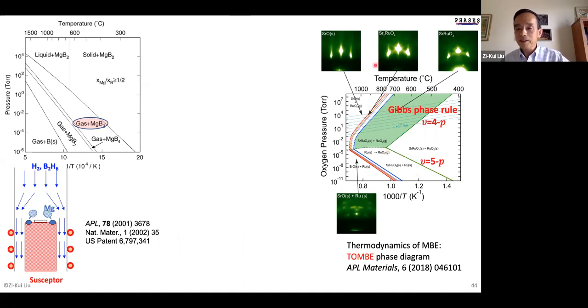This is from experiments, right? You see, experiments, you make 2 phases here, but here you make 1 phase. So your Gibbs phase rule was different. So the Gibbs phase above here is 4 minus P, and here it's 5 minus P. So you have 1 more degree of freedom here. Why is that? It took us a while to figure out.